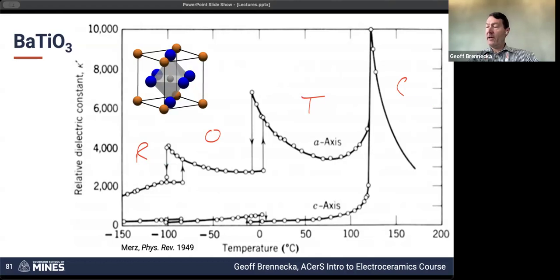So we've got cubic, the high temperature, tetragonal at lower temperatures, orthorhombic, and then rhombohedral below that. And at each one of these phase transitions from one of those symmetries to the next, we see an increase in permittivity, the largest of which happens between the tetragonal and cubic. So if we want a really high permittivity, then we probably want to be somewhere near one of these phase